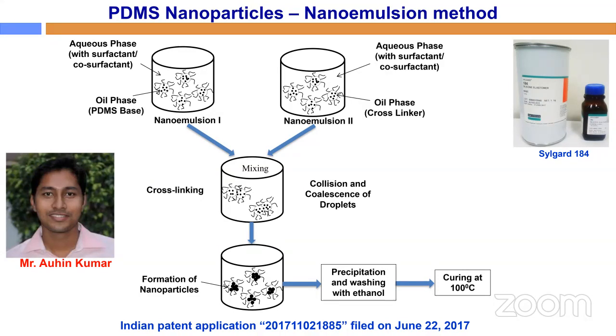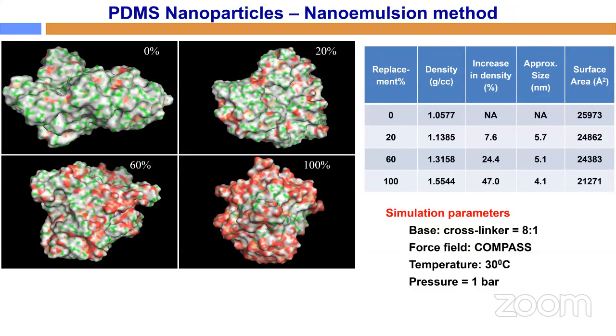Since he has a molecular dynamics background, he did some molecular dynamics studies. Why is this PDMS not stable? Why is it forming a film? So he took the 0%, the leftmost corner one, where only PDMS is present and there is no hydroxyl group. But when he increased the hydroxyl group to 20%, 60%, 100%, all this PDMS converts into a spherical shape, or rather it comes to some kind of a finite shape.